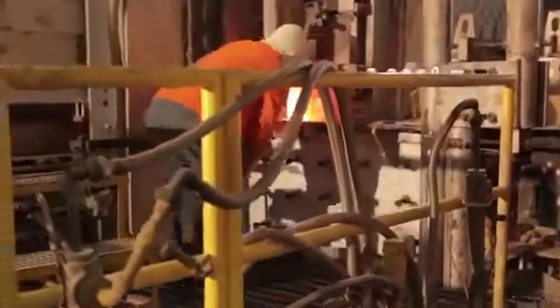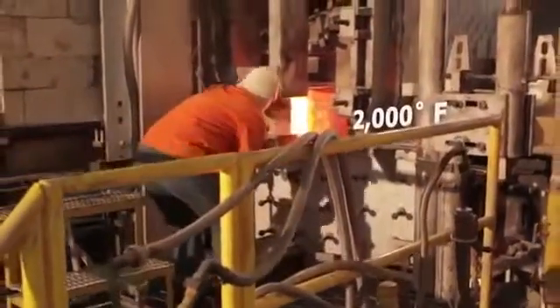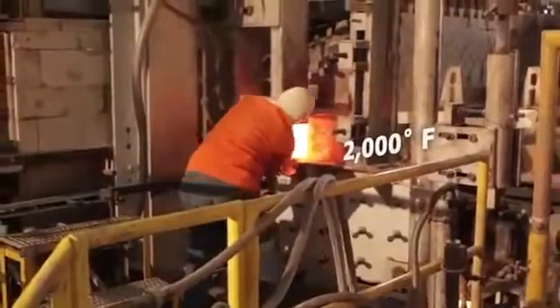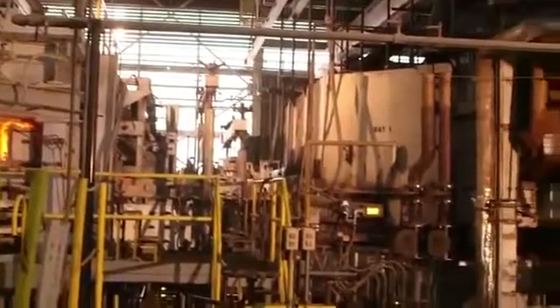Inside the furnace, heat is applied from alternate sides in 15-minute cycles. This assists fuel efficiency by ensuring that combustion takes place in the presence of preheated air. This continuous melting process can last as long as 50 hours. The glass leaves the conditioning end of the melting zone at a temperature of 2,000 degrees Fahrenheit through a narrow canal where it passes to the heart of the process, the tin bath.